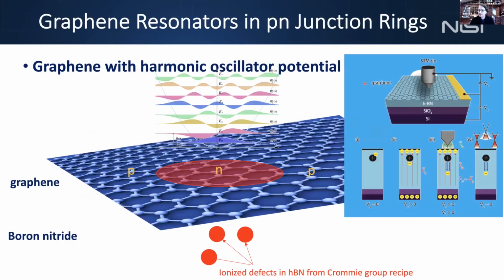So we have to create the PN junction, and I'm not going to go into great detail. You can look at the references, but we're using a recipe that was developed in Crommie's group, where we ionize defects, native defects that are in the hBN layer. So if you pulse the tip at a high potential, you ionize these defects, and the defects create a fixed polarization in the hBN insulator, which stays there.